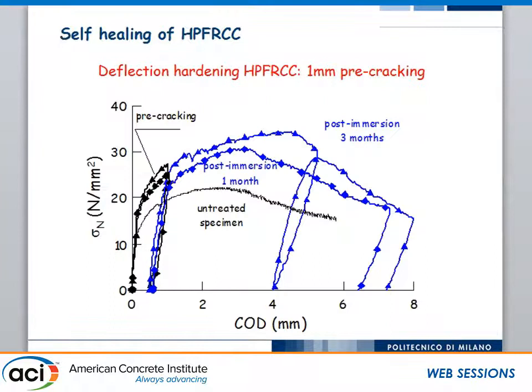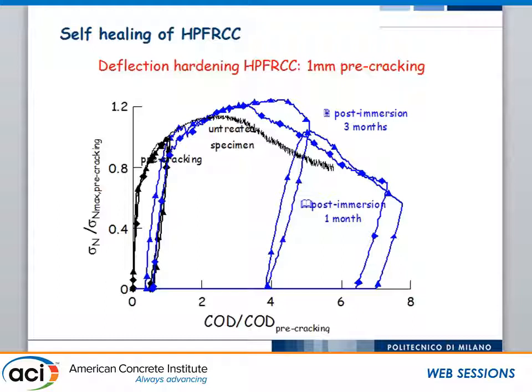And so you could see these are some results for the 1 millimeter crack opening. This was our reference specimen, which for some reason had somewhat lower performance, so it's much more interesting to compare them in dimensionless quantities. So this is the untreated specimen. After 1 month, you get this response. After 3 months, you get this response here. So you have clearly, with reference to the same pre-cracking level, an increase of both the load-bearing capacity and also of the ductility, because the peak stress would occur at this crack opening level for a monotonically loaded specimen up to failure instantaneously, but it also increases when you expose it in water.